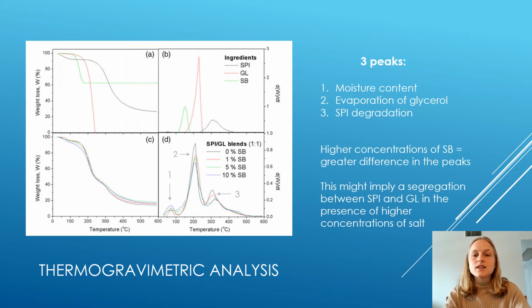For the blends, we can see that they follow a similar pattern. They peak at around 75 degrees due to moisture content, then peak again at 210 degrees due to the glycerol content that evaporates, and finally peak a third time at 305 degrees when the soy protein isolate degrades. On the graph D, it is possible to observe that the first peak is higher when the SB concentration is greater due to the hydrophilic character of the salt. However, the last two peaks are lower with increasing SB, which might imply a segregation between SPI and GL in the presence of salt.